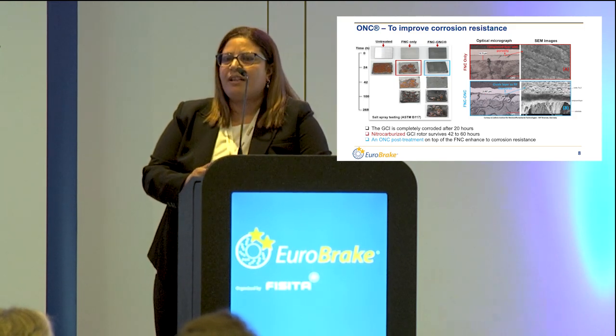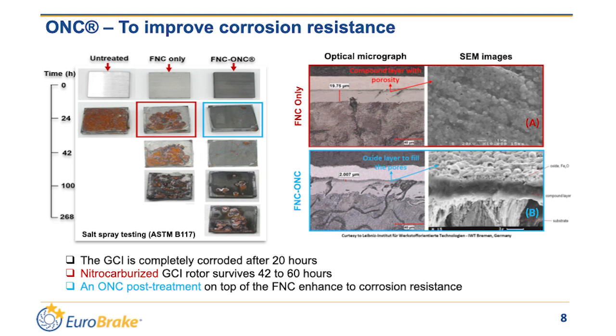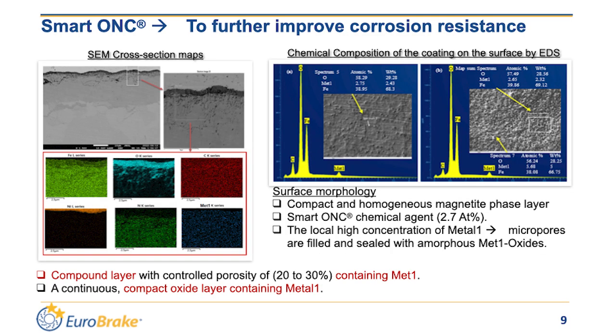The SEM images show that there is some porosity on top of the compound layer, especially near the graphite flakes. And if we apply a post-oxidation, the oxides will fill the pores and form a thin top layer that enhances the corrosion resistance. To further improve the corrosion resistance, we developed Smart ONC, which is an in-furnace controlled post-oxidation that contains